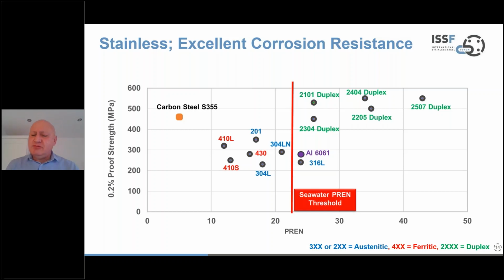So to the left of that line, these products are not really suitable for seawater applications. To the right, materials are, and this is a guide. Don't think this is an absolute marker in the ground, because of course seawater conditions change depending on where you are in the world, but this just gives you a simple guide. So aluminium sits just to the right of that line, close to 316, but lower in strength. And then moving into that top right hand section, you have the family of duplex stainless steels. So I think this chart shows quite easily, if you're looking for that combination of strength and corrosion resistance, where you need to be considering your material choices. And of course, I could have littered this chart with many more alloys, but we're talking primarily about stainless steels, and we're looking to compare that with other regularly considered construction materials in the steel family.